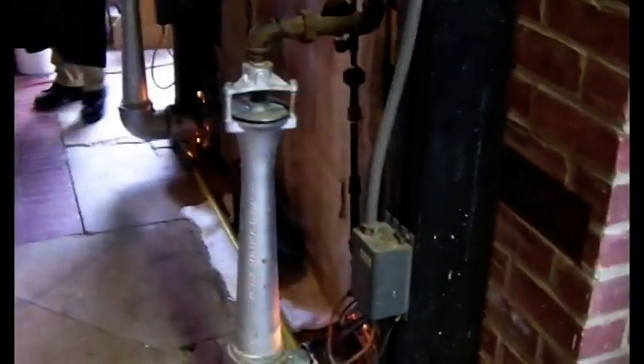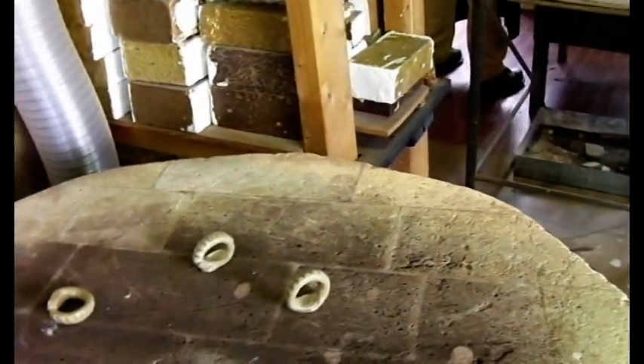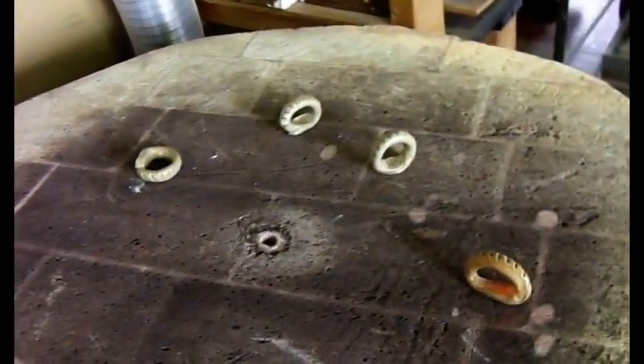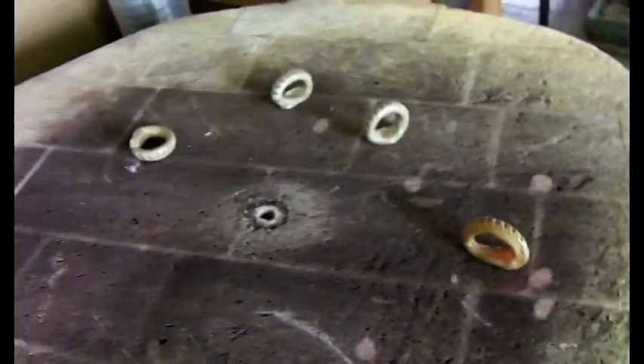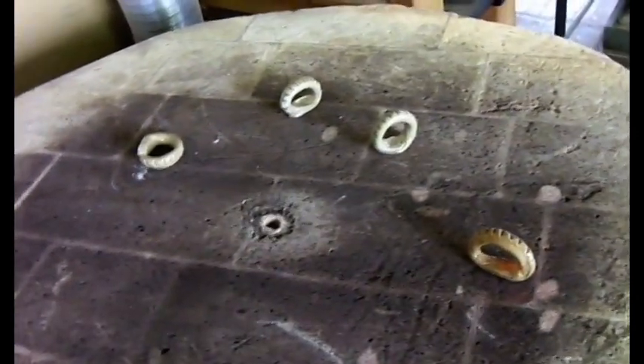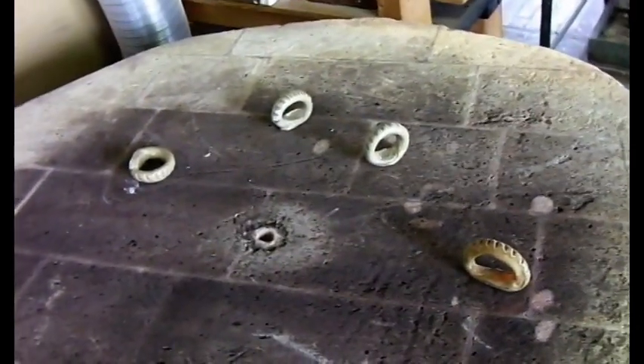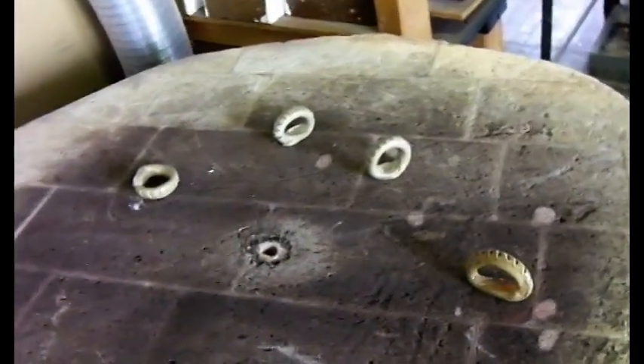So our kiln right now, we're at 2,375 degrees. We're going through a time of putting salt in the kiln. It's 3 segments of putting salt in the kiln, and then after this stage we soak the kiln for 2 hours, and then we'll turn it off, and it'll sit for 10 days before we open up the kiln and see what we got.